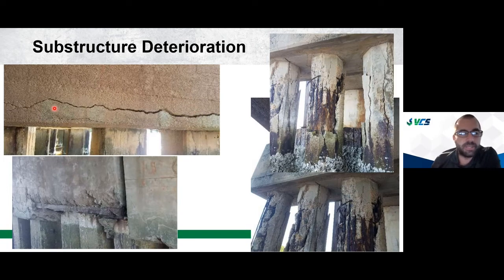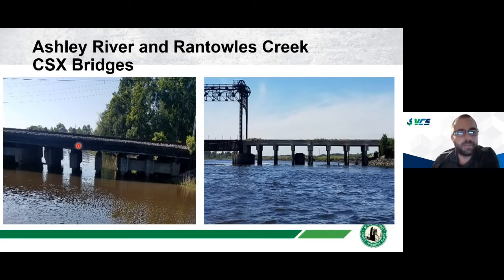Obviously some pretty serious damage. On the right here, you can see the piles are very, very corroded and deteriorated. Unfortunately, not very well maintained over the years. If I go back one slide, you can kind of see one of the bridges. So the one on the left, the pier caps are much closer to the water, whereas on the right, the structure, the pier caps are much higher off the water. And that really has a big influence on the condition of those elements.